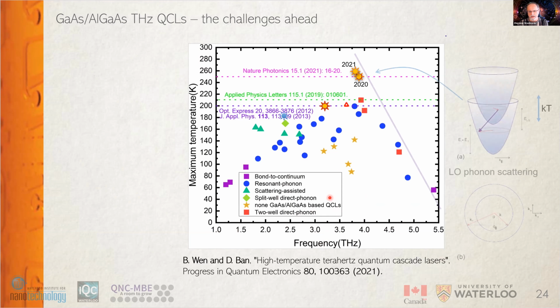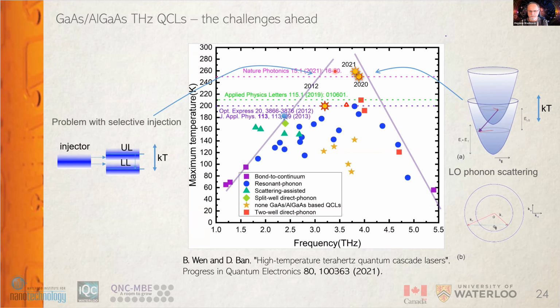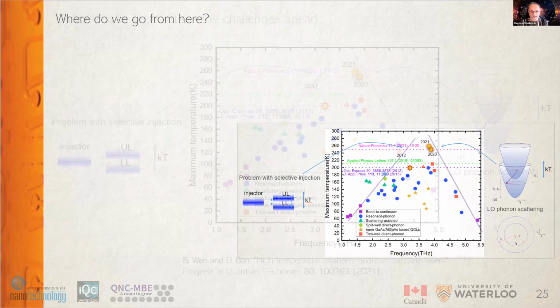And you can see here that there seems to be a bit of a pyramid-like structure. And the reason for that is that on this side, we start to have problems with the population by this LO phonon, which we are using to quickly depopulate lower lasing levels. So this is really a challenging part to cross in this material system. And this part, on the other hand, is just difficulties with injecting the carriers selectively to the upper lasing level.